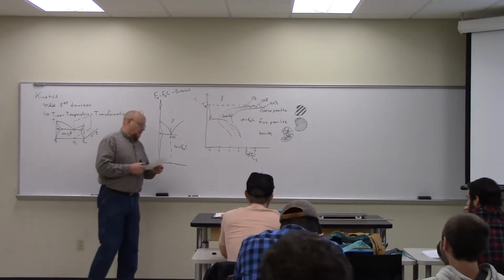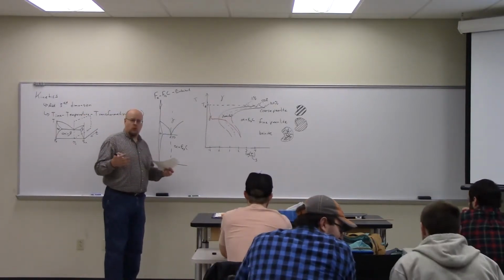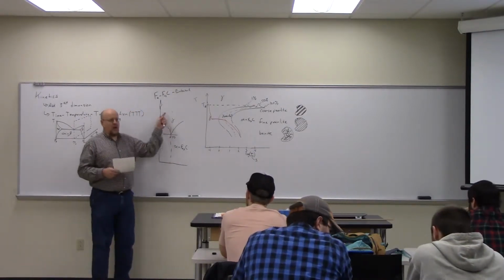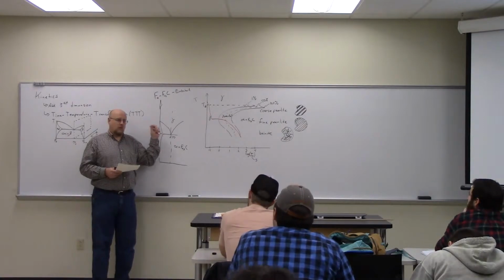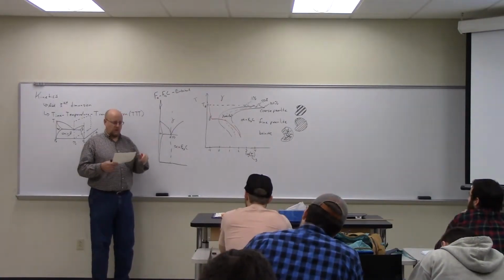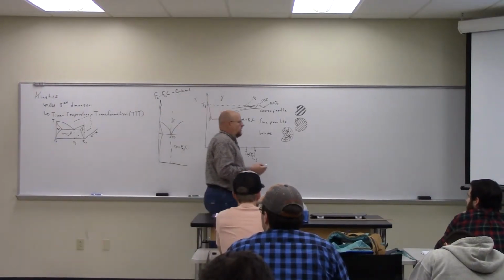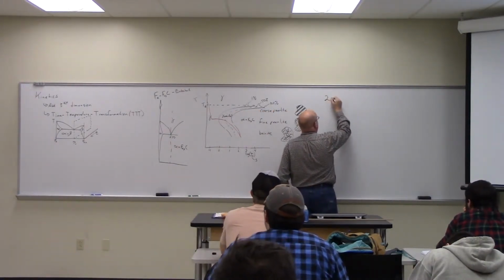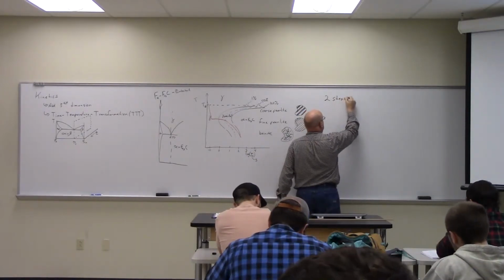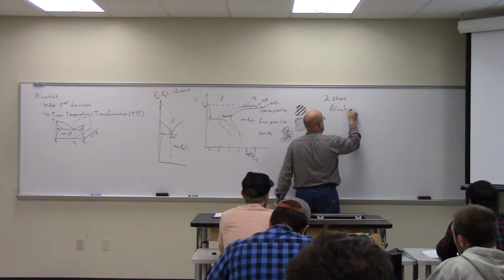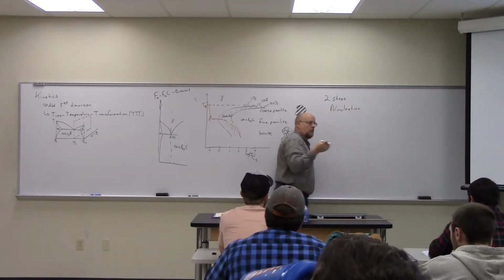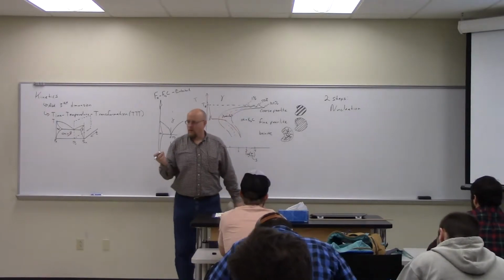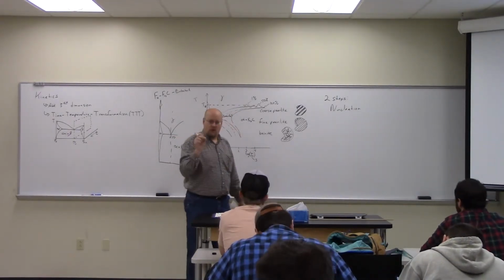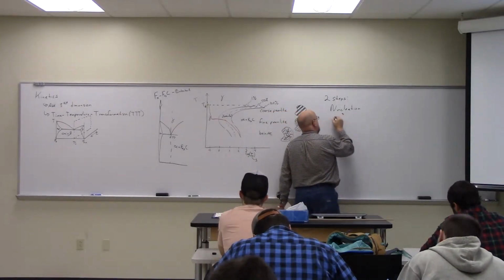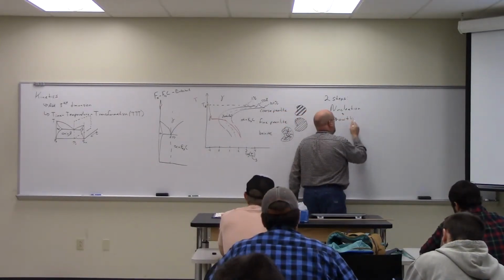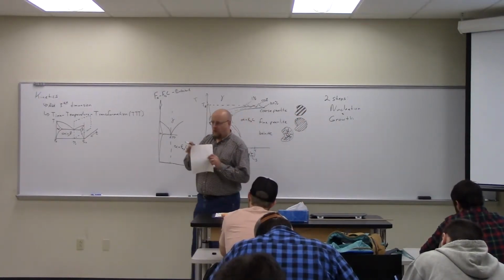These are primarily driven by diffusion. We have to diffuse the atoms that are trapped in the gamma out to the edges in order for them to transform into alpha. It's a diffusion-driven process. So there are two steps. There's nucleation. That is, we have to start the grain somewhere, like I was talking about with the boiling water last time. You have to have some place for the reaction to start. And then you have growth. Once you have a seed, you start building on that seed.